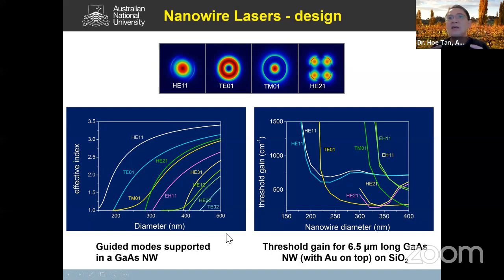Obviously you want to have some effective refractive index because you want to have a waveguide, an optical cavity. If you look at this, if you go to very small diameter nanowires, you don't have any refractive index contrast with respect to air, so you will not form an optical cavity. To form an optical cavity, you need to go to larger diameter nanowires, and you can see now we have some refractive index contrast. This can happen depending on the mode that you are interested in.